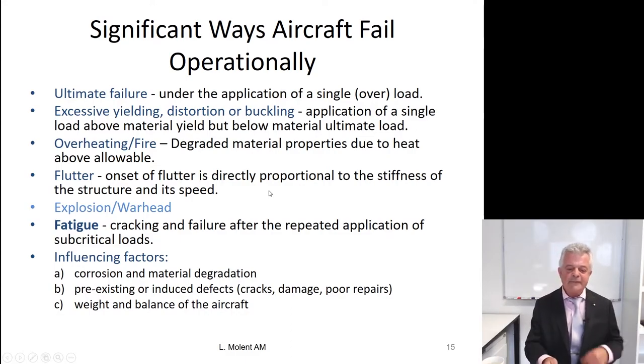Significant ways an airplane may fail operationally. We've spoken about ultimate failure. You exceed the flight envelope, you overload the airplane, things may go wrong. You can also degrade the airplane by excessive yielding, distortion, or even buckling of the airframe. That may not lead to instantaneous failure, but may lead to things like control surface jamming, which leads to the airplane not being controllable. And that's just as bad a problem. So excessive yielding, buckling, twisting, okay?